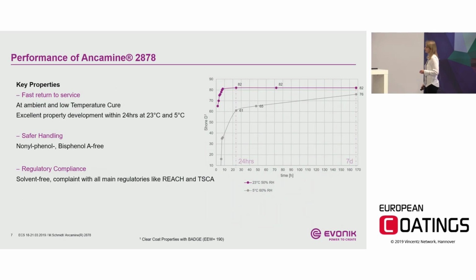So now a little bit more detailed. Fast return to service. We're talking about property development. We have looked into the property development in Shore D hardness, which you can see here on the right side. We're looking at low temperature, that means 5 degrees Celsius, and room temperature, 23 degrees Celsius. Here you can see that within 24 hours we have reached a high Shore D hardness. At 5 degrees we reached 61 Shore D, and at room temperature, a Shore D from 80 to 82. And this is what we mean with the fast property development at ambient and low temperature cure.